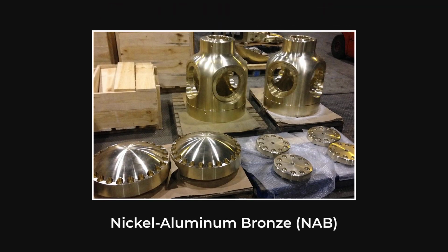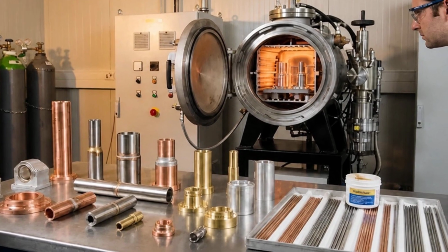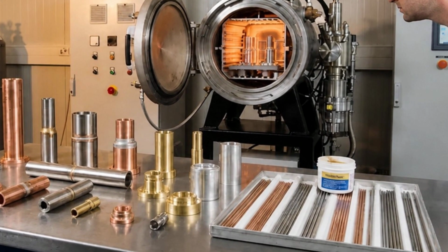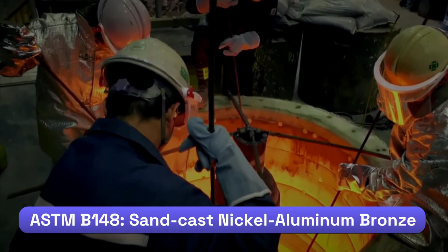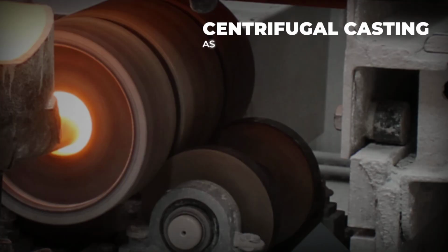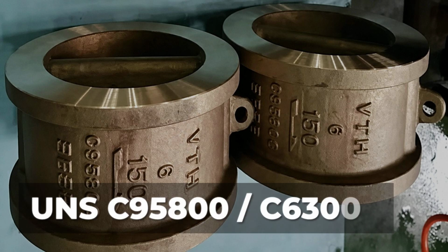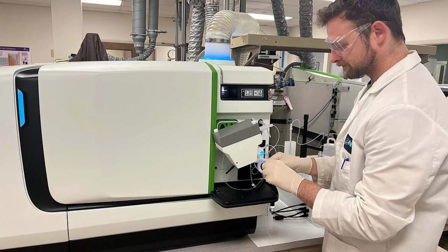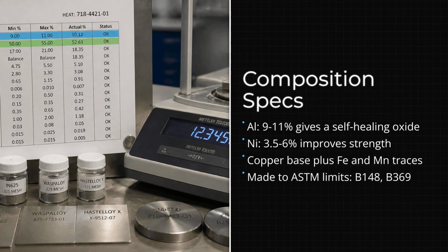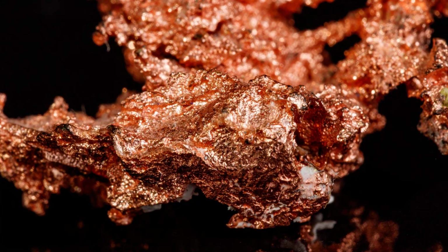The modern answer to this challenge is cast nickel aluminum bronze, a specialized copper-based alloy engineered specifically for high-stress marine environments. In maritime manufacturing, this material is governed by strict specifications: ASTM B148 for sandcast components, and ASTM B369 for centrifugal castings, typically designated under the Unified Numbering System as C95800 or C63000. Within these standard grades, the chemical composition is tightly controlled. The alloy contains roughly 9 to 11% aluminum and 3.5 to 6% nickel, built upon a base of copper and small additions of iron and manganese. It is this precise chemical blend that dictates how the propeller surface interacts with the surrounding ocean.